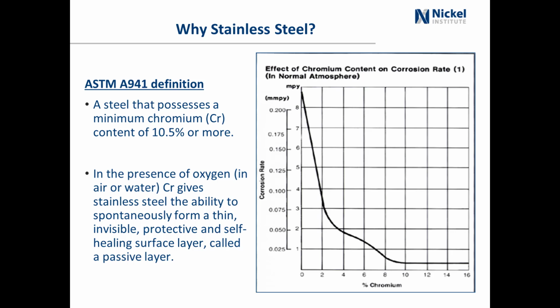And this is demonstrated in this chart here, where we're looking at the chromium content in various different types of steels. So if you were to take steels of these varying chromium contents and hang them on a tree outside this building and then measure the corrosion rate, you're going to get a curve like this, and you're going to see that once you get down to about 10%, then it flat lines out. It doesn't matter whether it's 10% or 16%, you have a very low corrosion rate. And so that's why 10.5% is the minimum chromium content for a stainless steel.